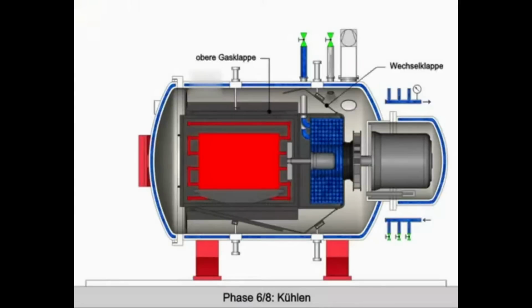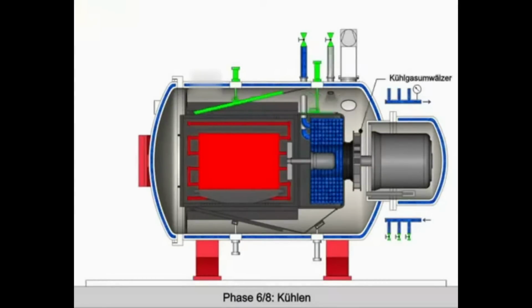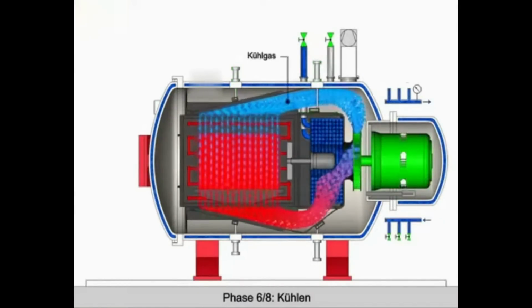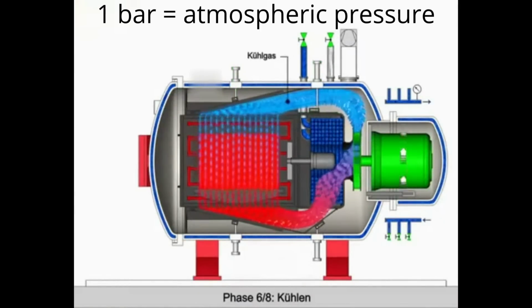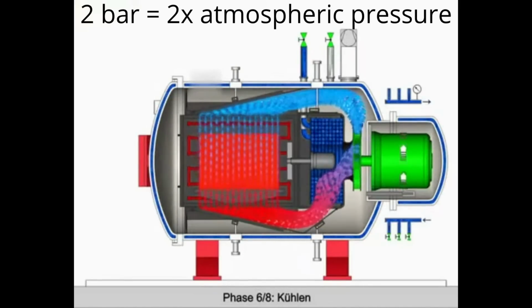The most common quenching method for factories is a pressurized nitrogen gas quench. The pressure of the gas is typically rated in bars, where a 1 bar quench would be atmospheric pressure and 2 bars would be double atmospheric pressure. The higher the pressure, the faster the speed. However, this is not the only factor that matters.